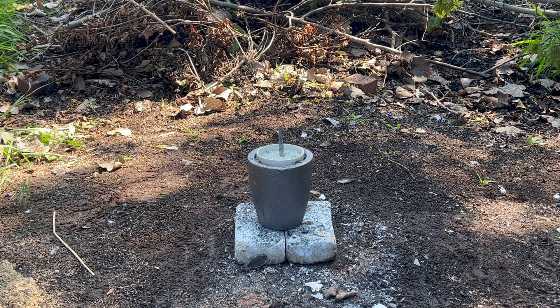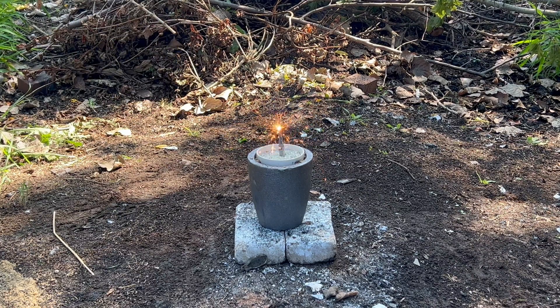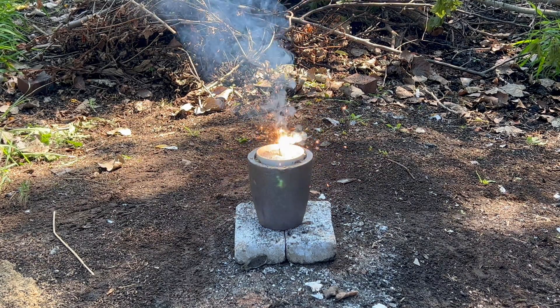I used a larger crucible filled with sand to keep the reaction vessel together. Without it, the ceramic shatters and all the boron is lost, as shown in the opening clip. The reaction is started with a piece of magnesium ribbon and sparklers. This is a thermite reaction: the magnesium strips away oxygen from the boron trioxide to produce magnesium oxide and boron metal. The sulfur was added to form magnesium sulfide, which produces heat and helps the reaction forward.